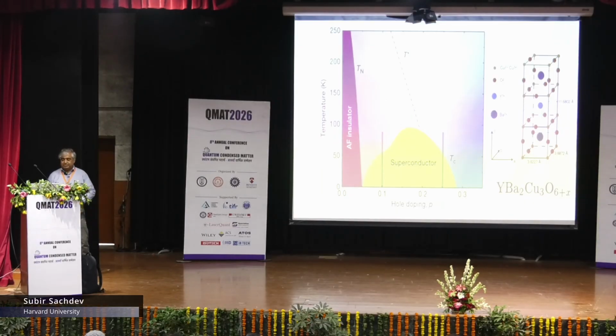All right, so this is the famous phase diagram of the high temperature superconductors. This is the temperature axis, and this is some axis where you're controlling the density of electrons in a copper oxygen plane here. I'll go into the details a bit later. Okay, so as you change the density by varying the oxygen concentration in this crystal, you get the high temperature superconductor up to a temperature of 100 Kelvin and even higher.